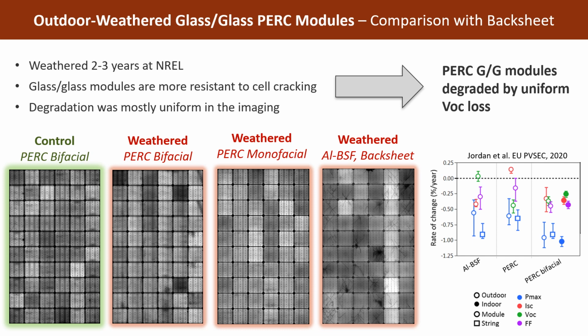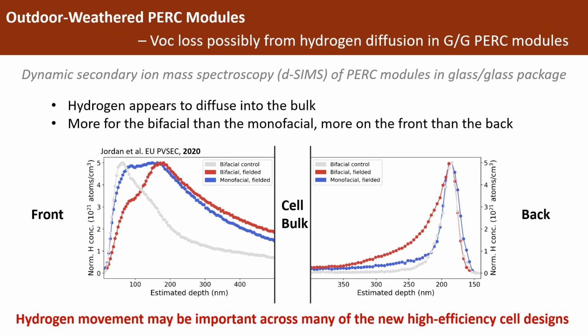In terms of the different processes for cell degradation, we see that the PERC modules tend to degrade more in VOC, while VOC degradation is not typically the primary degradation process in the older generation modules like aluminum BSF. And you might have recently heard Dirk Jordan speaking about this type of VOC degradation at conferences, where this new type of degradation process seems to occur in higher efficiency modules like PERC and silicon heterojunction. We believe that the VOC degradation process that we observe may be associated with hydrogen redistribution in higher efficiency cells, which affects the cell's passivation quality.